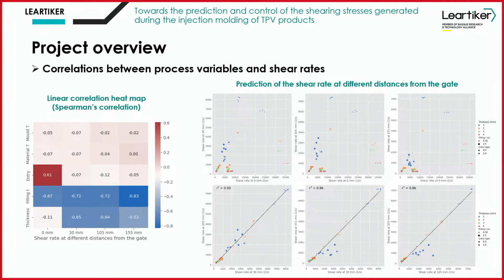So as I said, considering this, what we thought was, okay, so if we have these correlations between process parameters and the shear rates, are we able to generate a comprehensive model to predict which is going to be the shear rate in different positions of the plate, because as I said, we want to have an idea locally which are the effects on the shear rate. So we analyzed if we are able, by knowing the shear rate at one position, to predict the shear rate in the other positions.